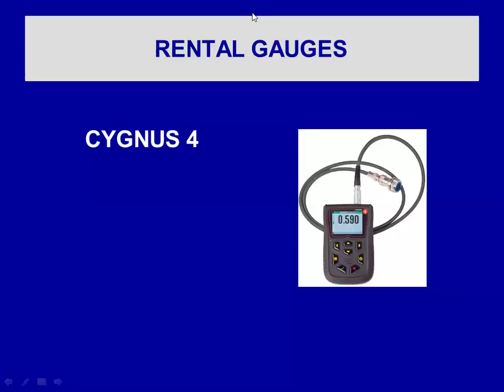The problem with digital gauges is that the information it gives you is digits. It doesn't tell you if it's inclusions, laminations, hydrogen, cracks, pitting. In many cases it is pitting, but it doesn't tell you that.